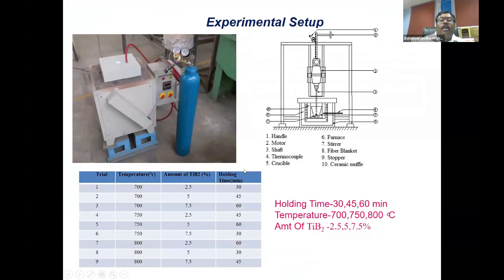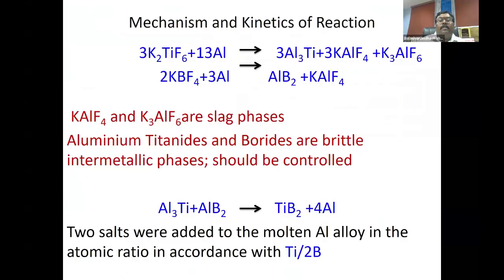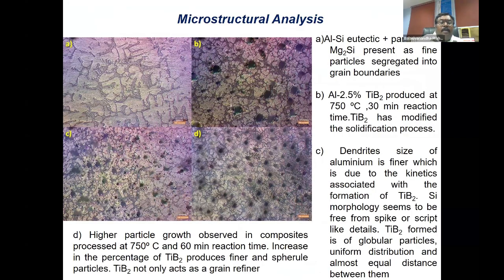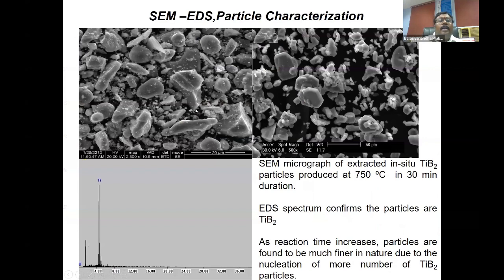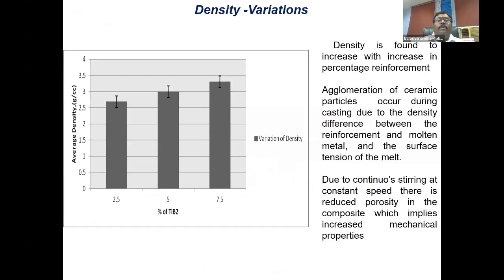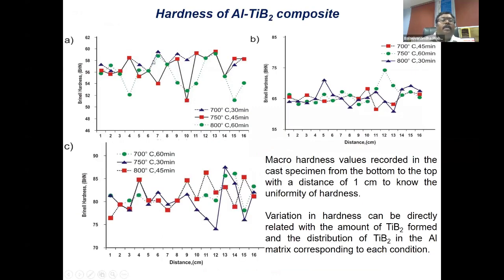I will skip it and demonstrate what is really behind these in situ reactions with microstructure examinations. After developing these reactions inside the melt, one could see that at any temperature, whether 700 degrees centigrade or higher, I could get a homogeneous distribution of reinforcement, because the particles evolve inside the liquid melt. So there is homogeneity in the particles, and the particles also have uniform dimensions. These are all separated particles, and on examination some are spherical and different shapes are there.